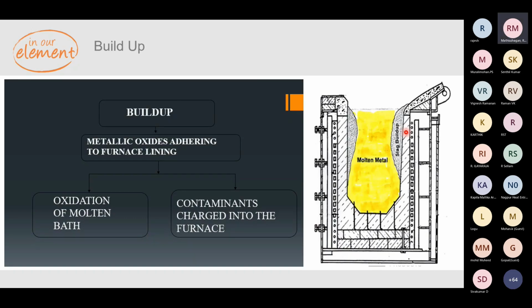So buildup, it's because of the oxide formation, metallic oxides adhering to the furnace working lining. It can be oxidation of molten metal and contaminations from the charge into the furnace. So this will reduce the volume of your metal, and because of which the power rating is also increased, and then you tend to break the lining.